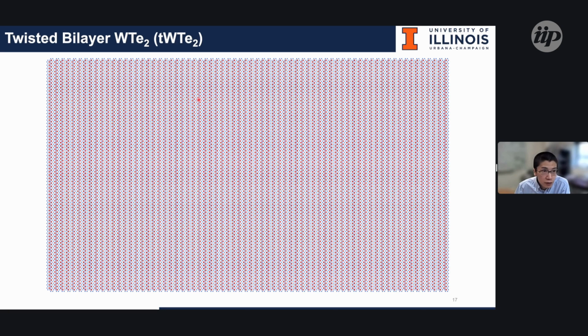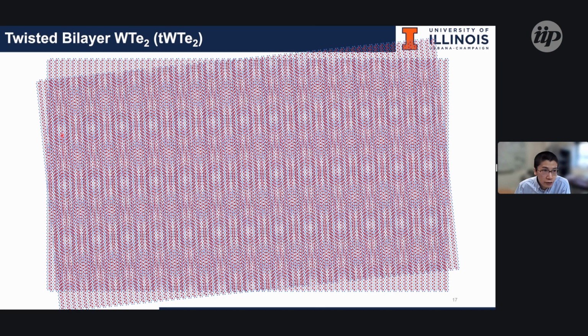With the twist, we were able to see the Moire, which forms the rectangular lattice. With such a rectangular lattice, if I remove all the tellurium atoms, you can see that it forms a quasi 1D structure. Overlap mostly here, less overlap here, and then you can see the interchanging between these wires. We call it AA for the most overlap region and AB for the less overlap region.